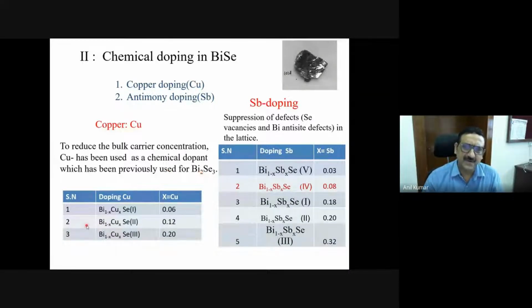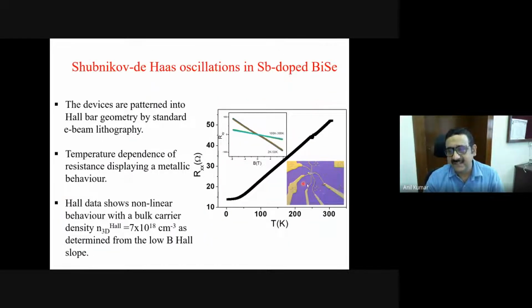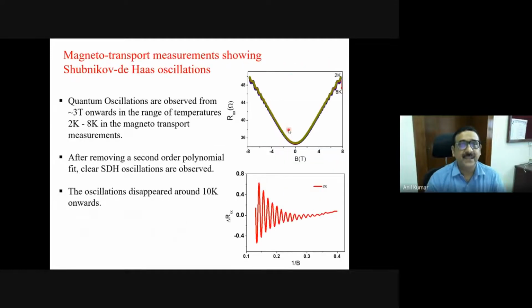So we did copper doping, we did antimony doping, and maybe I will just describe one such experiment with 8% antimony doping. Again, we grow the single crystals and we start exfoliating the way I showed you earlier, and then we make devices out of it. Then again, unfortunately, this is not a bulk insulating material. It is like bulk conducting, but it has got very good surface states. But I would like to see, as time progresses, that I get a metal insulator transition in this kind of structure as well, so that we have the ideal crystal.